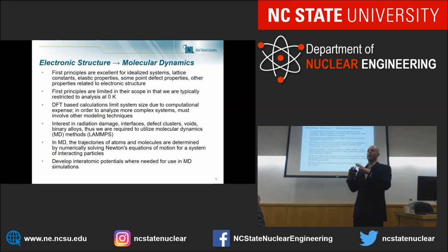This is all well and good. We can get a lot of interesting properties from this type of work. However, it's limited to fairly small systems. We are limited to doing about 250 atoms. You wouldn't want to do systems much larger than that. You're also typically limited to calculations at 0 K. There is now some ab initio MD work where you can look at systems at non-zero temperatures as well, but that's still an emerging field somewhat, and it still limits your system size.